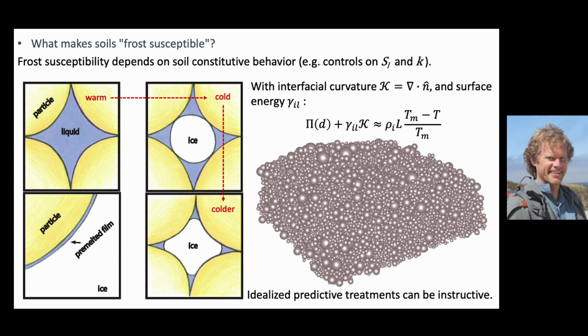So the pre-melted film is there because of interfacial interactions that we saw in the thermodynamics arguments. So it was that interaction potential between ice and the substrate. So you can think of it as a wetting phenomenon. If I think in this room right now, we're probably at 40% relative humidity, something like that. And yet, if you were able to interrogate many of the surfaces, say the window over here, you would find a few molecular layers of water, condensed phase, on that surface. And it would depend upon the properties of the surface, of course. But that condensed phase is there because it lowers the overall internal energy of the system, even though we're not at 100% saturation.